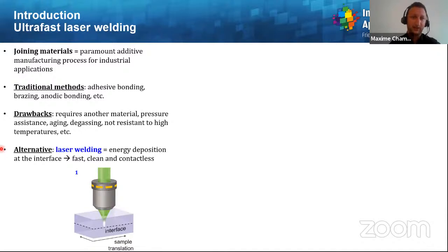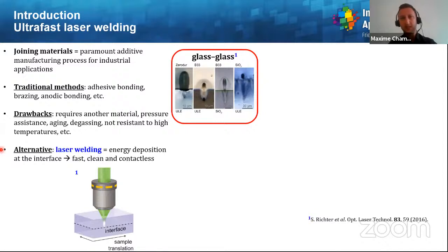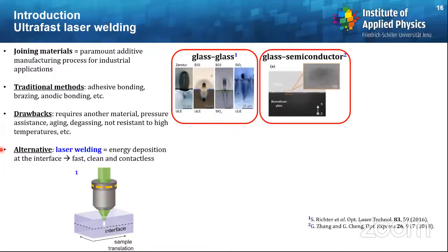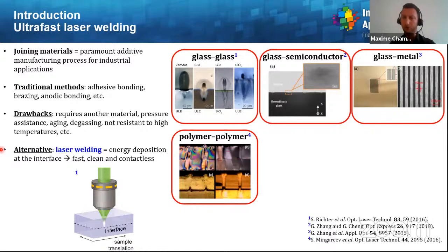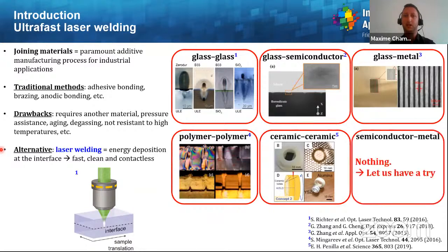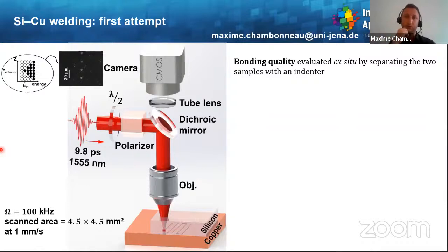An alternative was developed to solve this problem, which is called laser welding, which consists of energy deposition at the interface between two materials, as illustrated here. This provides a fast, clean, and contactless way to join those two materials. This was shown to be applicable in many material configurations, such as glass to glass, glass to semiconductor, glass to metal, polymer to polymer, and more recently, ceramic to ceramic. However, in the semiconductor to metal configuration, there is nothing too convincing so far. So let us have a try. To do so, we will use the setup illustrated here, and we will use silicon and copper for illustrating semiconductor to metal laser welding.